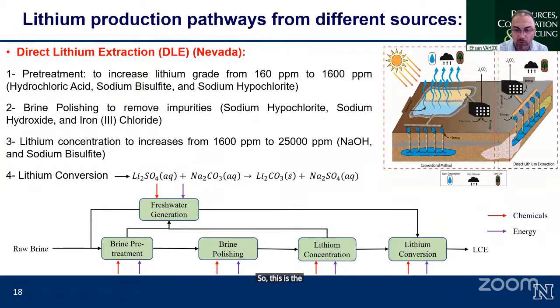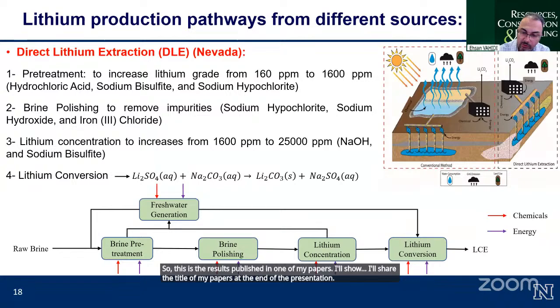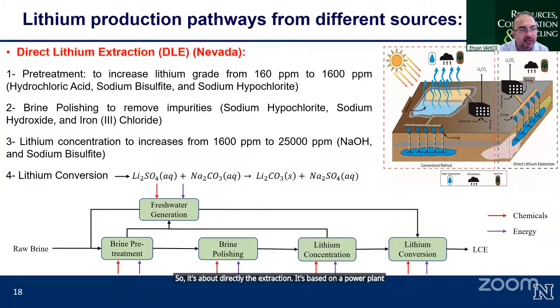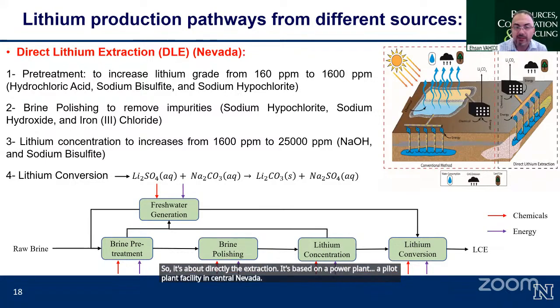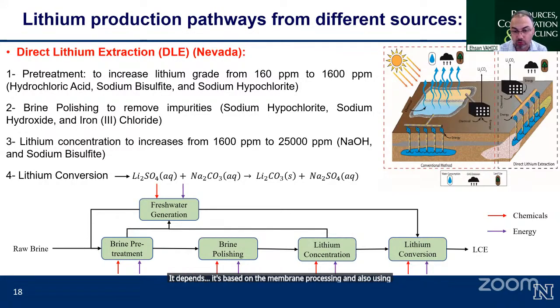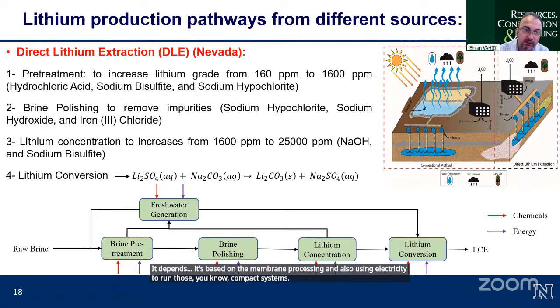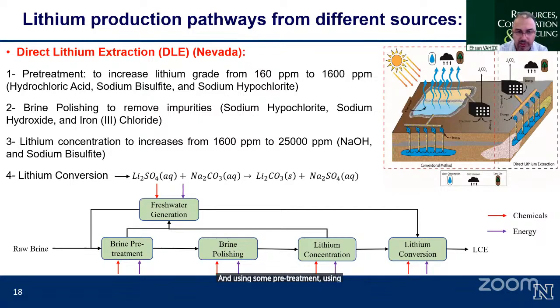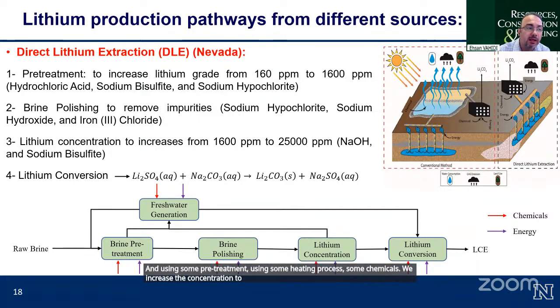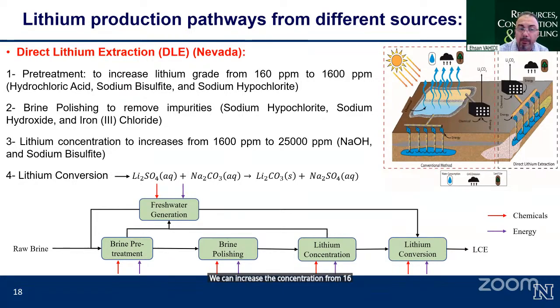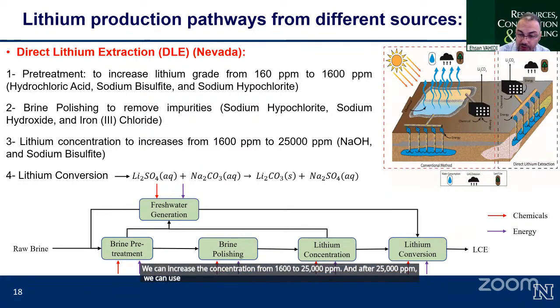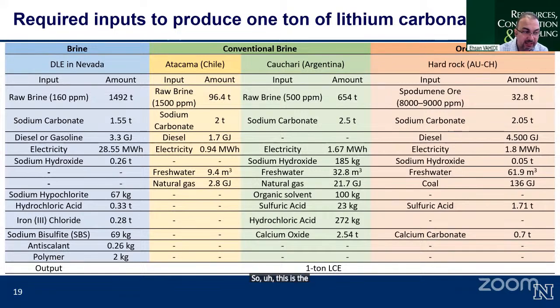These are the results published in one of my papers. I'll share the title of my papers at the end of the presentation. It's about direct lithium extraction, based on a pilot plant facility in central Nevada. It's based on membrane processing and also using electricity to run those compact systems. We start with the brine concentration around 160 ppm, and using some pre-treatment, using some heating process, some chemicals, we increase the concentration to 1600 ppm. And after some brine polishing, removing some impurities, we can increase the concentration from 1600 to 25,000 ppm. And after 25,000 ppm, we can use soda ash to precipitate lithium, and we can produce lithium carbonate in a very compact system.